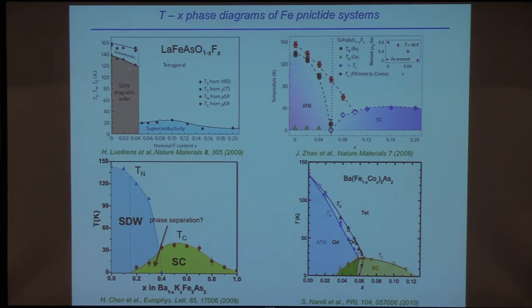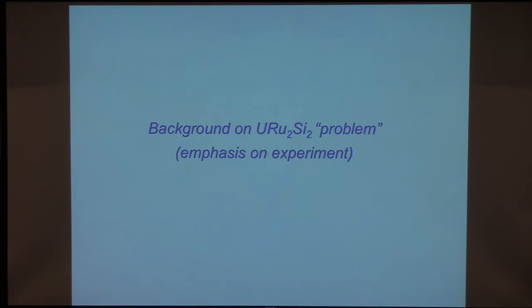Okay, and so this happens in all kinds of materials. I'm just showing you another example. These are some iron-based superconductors, and it occurs in the cuprates and many other heavy fermion materials. And this just shows you different scenarios where you're, in this case, changing the fluorine concentration, in this case, the potassium concentration, in this case, cobalt. But you're always suppressing antiferromagnetism or spin density wave transitions, and then producing superconductivity that occurs in the vicinity of the quantum critical point, and in some cases it overlaps and even coexists. Okay? So anyway, that's just some background.